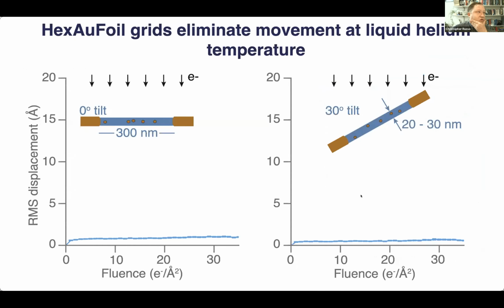And so I'll just show you very briefly an unpublished result so far, and that is imaging gold nanoparticles in small holes, even at about 14 Kelvin liquid helium temperatures, and we see that the movement is actually down below an angstrom. So this is encouraging, but we're not quite to the point where we're ready to collect data sets yet, because you have to understand all these details at low temperatures as well. So anyway, this is going to be fun, and this is a direction we're heading in.